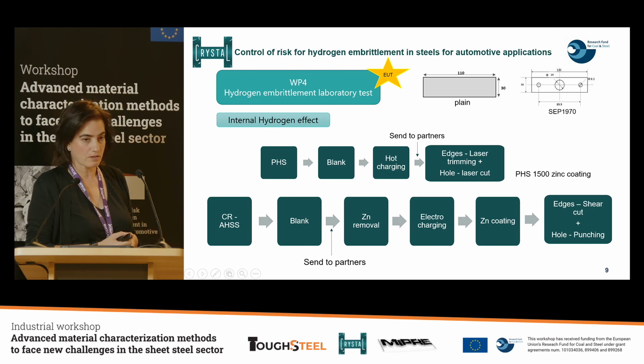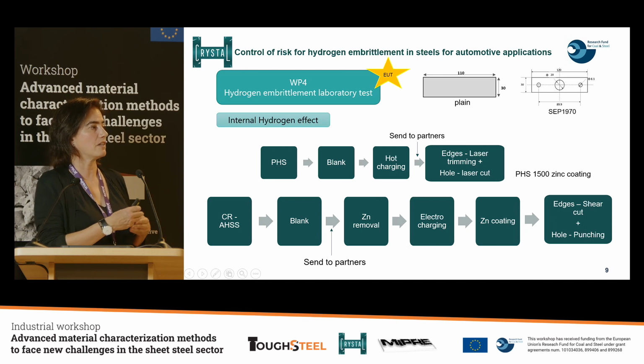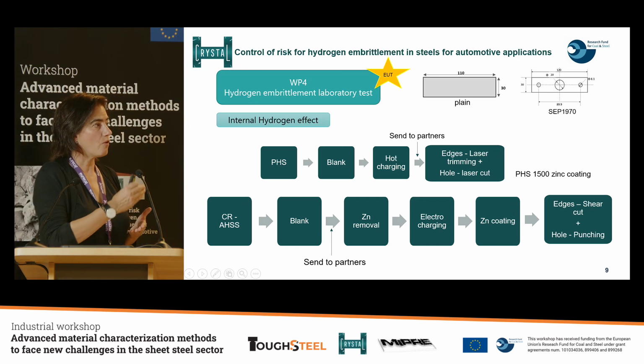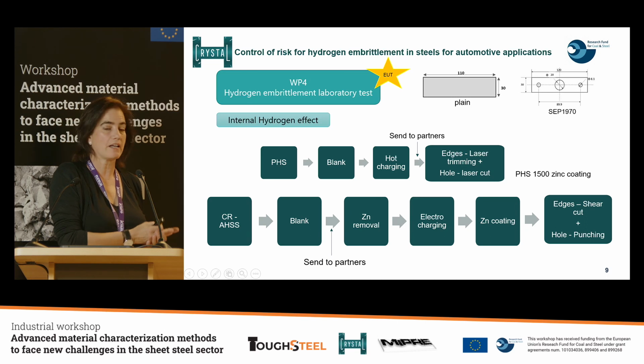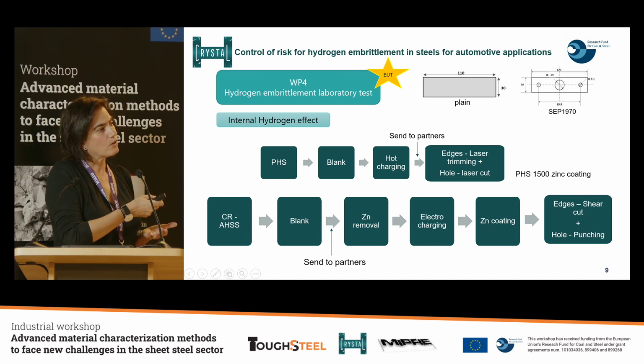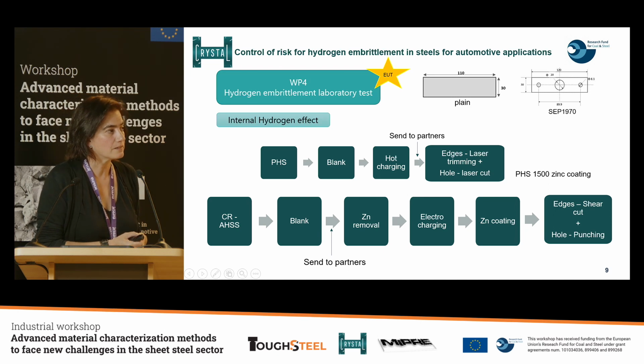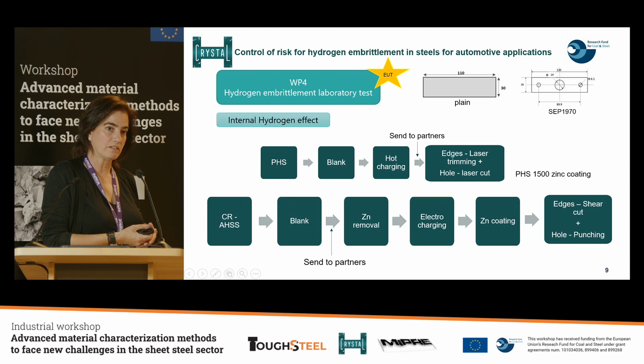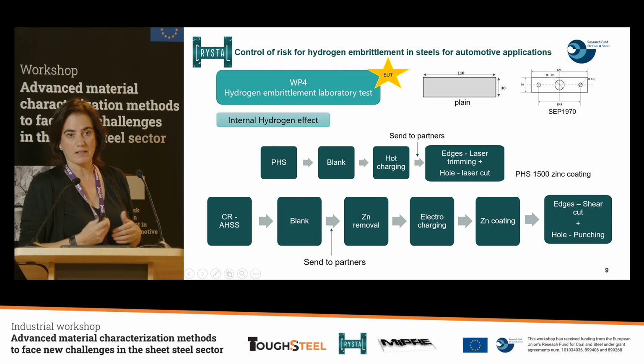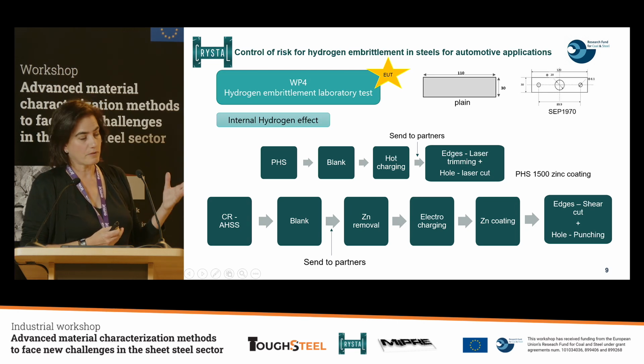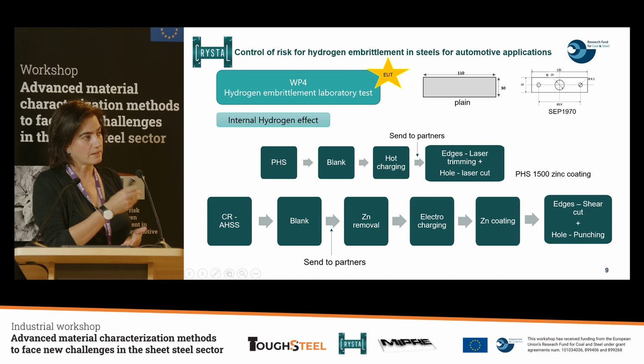In the case of the PHS steels, the PHS manufacturers send the blanks after charging, so they send the blanks to CRM, CRM charged the samples and then sent them to the partners. Each partner was responsible for laser cutting the edges and laser cutting the holes in this case. We have to include also that for the PHS steel 1500, we had to remove the zinc, charge the samples, and apply the zinc again. And in the case of cold-rolled steels, the steel manufacturers sent the blank to all the partners, and each partner was responsible for charging the samples. So as I said before, removing the zinc first, then electrocharging, applying the zinc coating again, and then we agreed to shear cut the edges and punch the hole.